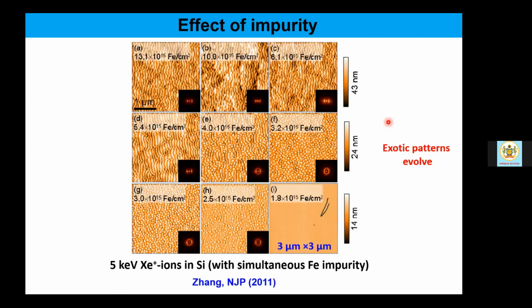You know, exotic pattern formation is also possible to be seen when we intentionally introduce impurities during the pattern formation. And you see, here the target is silicon, and energy was chosen to be 5 kilo electron volt.